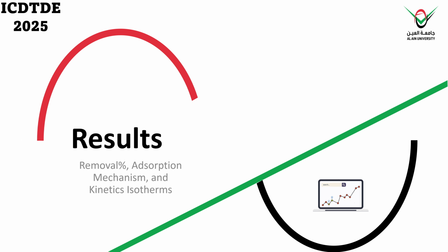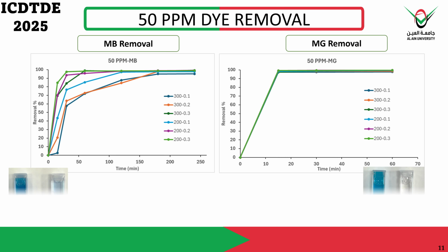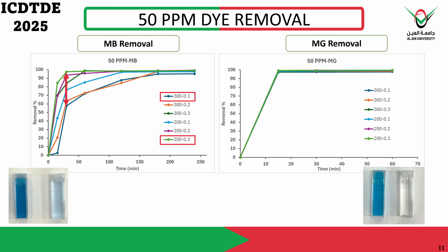In this section, I will discuss the results in terms of removal efficiency, adsorption mechanism, and kinetic behavior for both dyes. In the legend of the graph, each color represents a particle size and a dosage. For example, the color orange is 300 micrometer in size and 0.2 grams for the dosage. At 50 ppm concentration, higher adsorbent dosage and smaller particle size give us the optimal removal for MB.